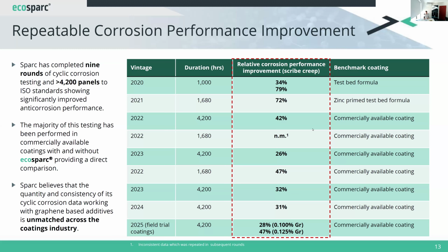We've done 9 rounds of this ISO 12944 testing since earlier this decade. This is a significant body of work, and we've seen repeatedly that the inclusion of our ecosparc additives within both formulations that we've developed, but importantly, commercially available coatings in this space, significantly improves the corrosion performance of those coatings. This is quite a harsh test, and it effectively measures the extent of corrosion from a defect that you put in the steel panel. And you measure that corrosion creep, and relative to the standard, you can determine the improvement or lack thereof through using, in our case, our ecosparc additive. So this data set is unmatched across the industry.